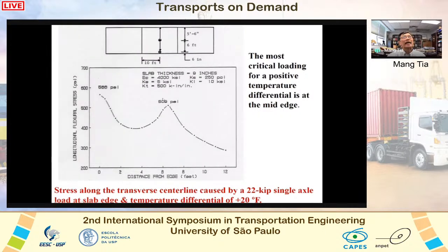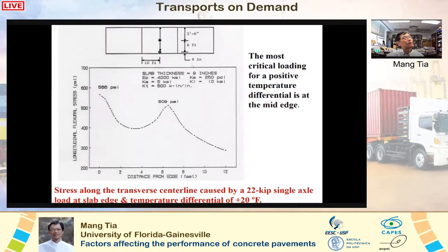Okay, and in the daytime, we also do analysis for the daytime condition when the slab is curled up at the center. Under that condition, the most critical loading condition is when the axle load is placed at the edge, as shown here. So one wheel would be touching the edge, and the other one is 6 feet away from this wheel. This is when we have the maximum stress. And in the daytime, typically, if we have a positive 20 degrees Fahrenheit, we have the worst condition. So to determine the worst stress in the daytime, we'll place this load here, and we use a temperature differential of plus 20 degrees Fahrenheit to determine the maximum stress.